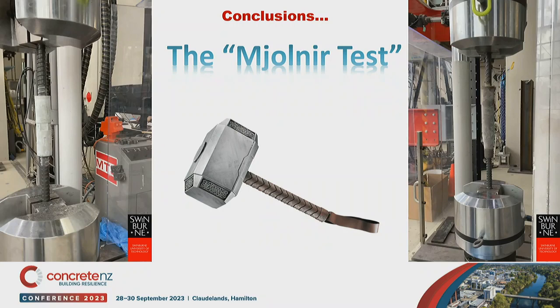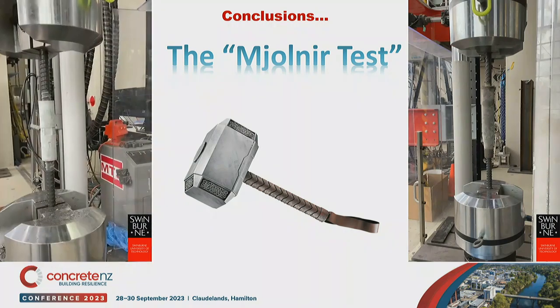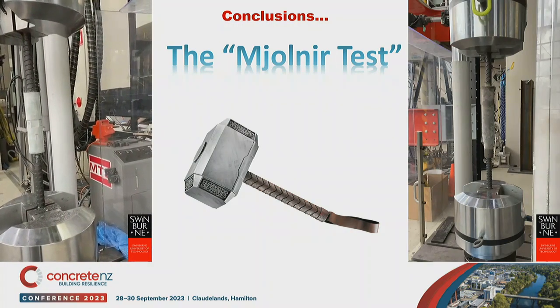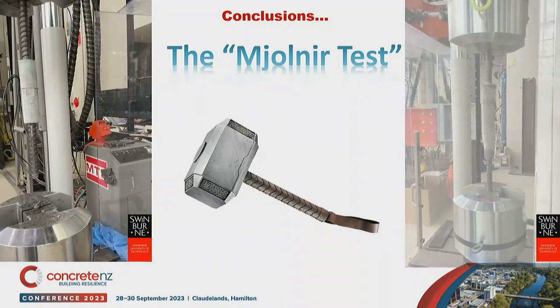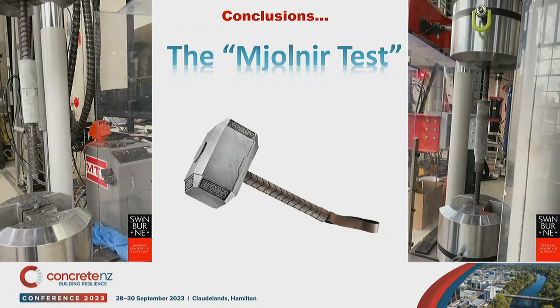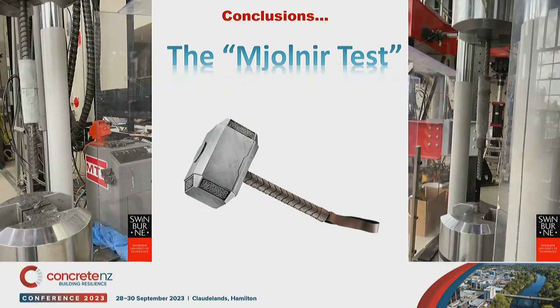We actually started this journey separately, and then we realized that we were traveling towards the same direction, and we joined forces. So what you see here is a couple of tests that with Reid we performed in Australia at Swinburne University. I had approval from the company to perform some trials. So what we see here. Testing in 3, 2, 1. That's how it looks like. It's very fast. That's what we want to see, a failure of the bar outside of the coupler.